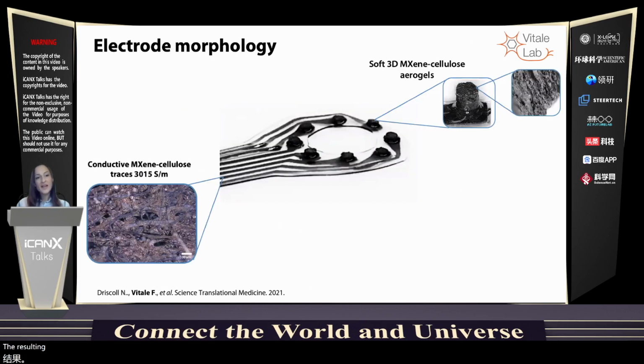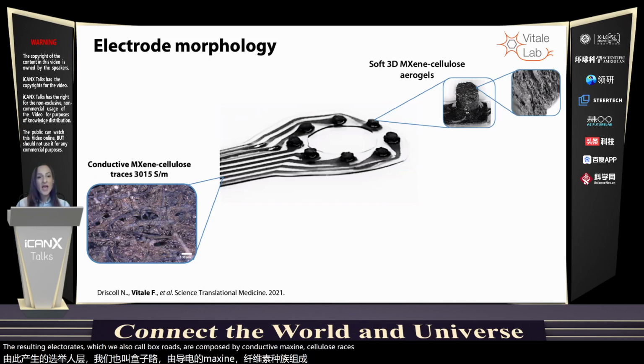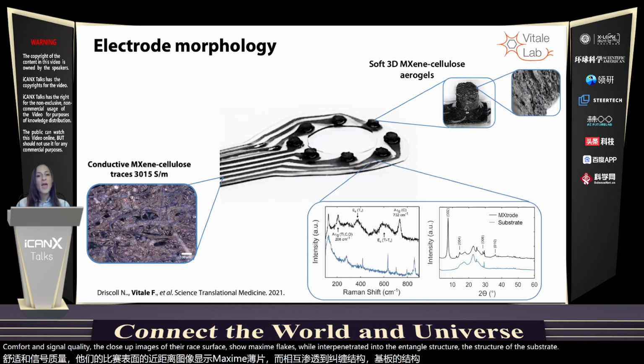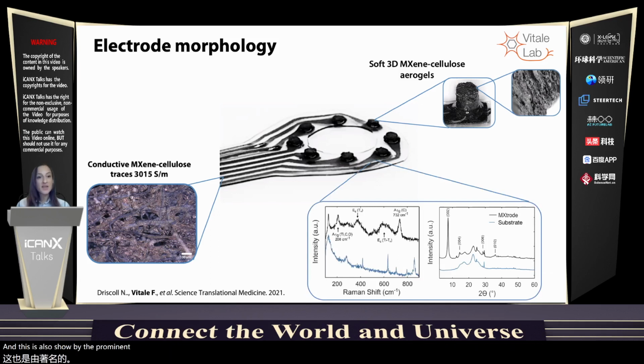The resulting electrodes, which we also call MXtrodes, are composed of conductive MXene cellulose traces and soft porous MXene cellulose aerogels at the scalp contact sites for improved contact, comfort, and signal quality. The close-up images of the array surface show MXene flakes well interpenetrated into the entangled structure of the substrate. And this is also shown by the prominent MXene peaks in the XRD and Raman spectra. The presence of these peaks also shows that the process is preserving of the MXene structure and non-damaging.